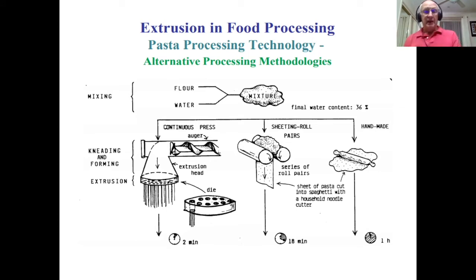And on the other hand, if we then go to a sheeting roll as a means of forming a pasta dough, then the process by multiple passes in a sheeting roll is much faster, but the mechanical work input resulting from the sheeting rolls leads to some temperature development, some damage to the starches and the proteins, and an elevation in temperature which starts to cause some of the starch granules to begin to rupture and release the starches. So we start to do damage to the starch. And so rather than pasta, which is meant to be a protein glue with starch granules embedded within it, it now starts to be a mixed system.